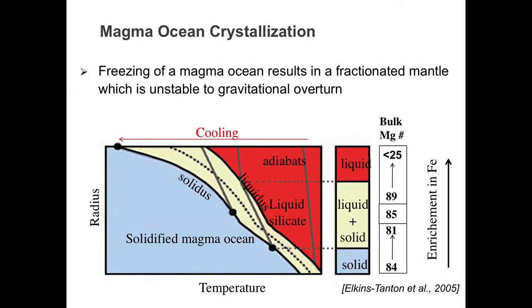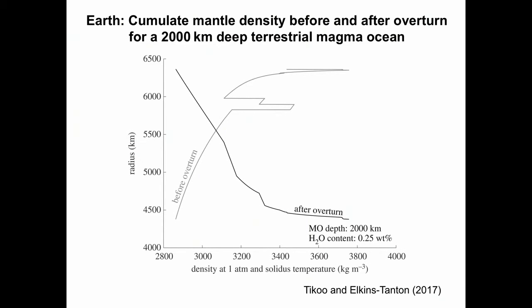And closer to the surface, we have less dense material. So that also, in addition, tells you that the first crust, which we probably have on the terrestrial planets, I come back later, and the moon is a bit different, is kind of an iron-rich crust. Whether that sticks there or sinks down depends on a lot of little tiny details. I don't want to go into that, but in principle that would be the first crust which forms on the planet. And if you have that sinking down, that is also kind of a vigorous process where you produce during that overturn much more melt, and then you would have at the surface a partial melting of that material here.